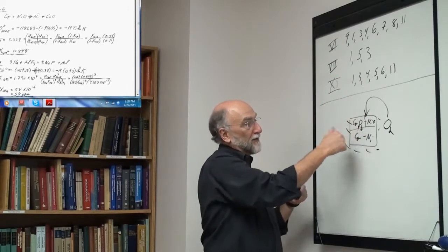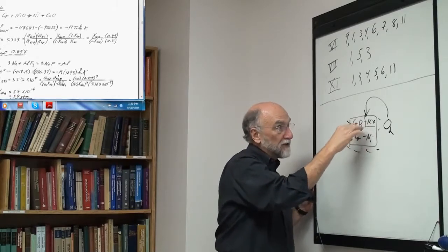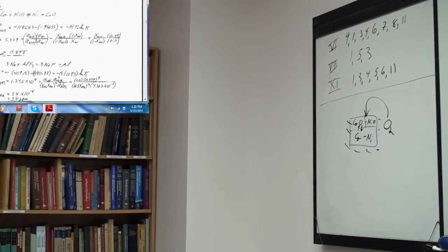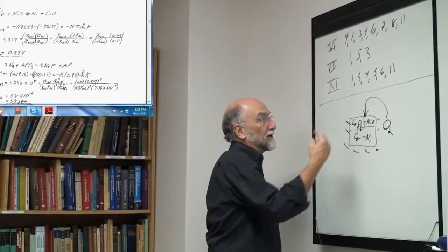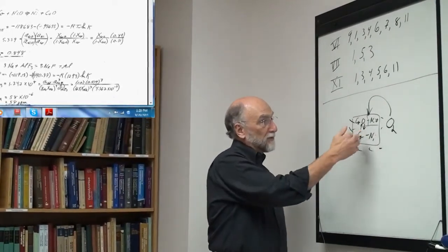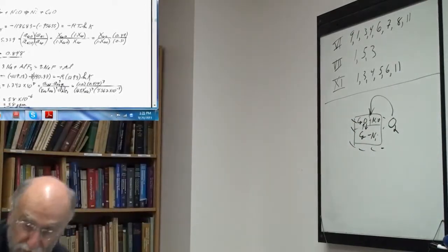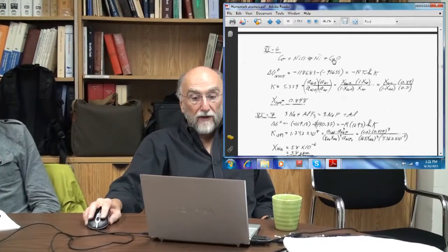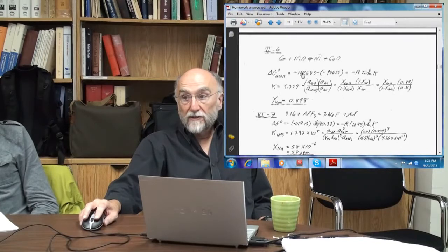If this goes on, the alloy continues to oxidize, but that's relatively slow compared to the fact that at the interface we're assuming we have an equilibrium. Okay, it's the same as bubbling oxygen. You could have iron silicon, and this is FeO-SiO2 liquid slag, and you're assuming that you're oxidizing the silicon, trying to get it up into the slag. Okay, so this is your exchange reaction between cobalt and nickel in one phase and nickel oxide and cobalt oxide in the other phase. So you always write the exchange reaction, which is the difference of the two oxidation reactions.